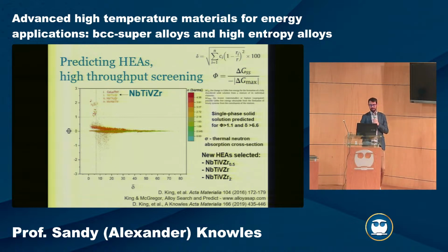And the idea here is that if we have these two parameters, we can then say alloys in the top left corner are likely to be a single phase solid solution. And this code takes 5 seconds to run. This was 100,000 compositions in about 5 seconds. It's a very simple code that just uses a data lookup type table to isolate the different alloys.